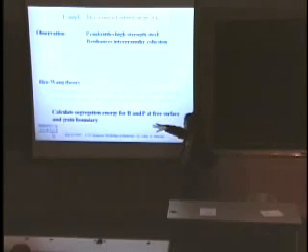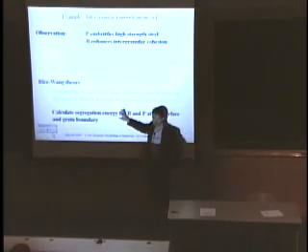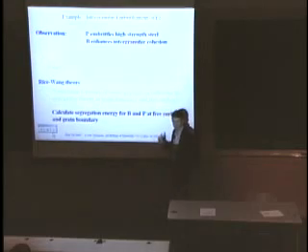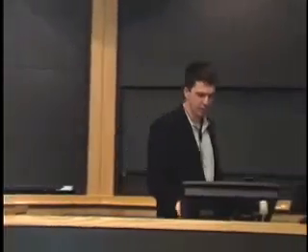If you have an impurity that has a large segregation energy to a surface rather than a grain boundary, then its presence is going to enhance surfaces, because it can have the benefit of that large segregation energy. So those are going to be embrittlers, because they will tend to promote decohesion. Whereas the ones that have a very large segregation energy at the grain boundary rather than the free surface will tend to promote cohesion. And so if you believe Rice-Wang theory, then this problem is very simple. All you have to do is calculate segregation energies. And that you can do.